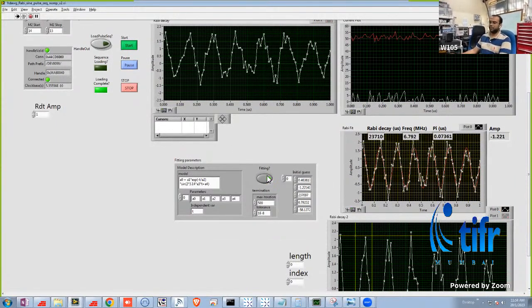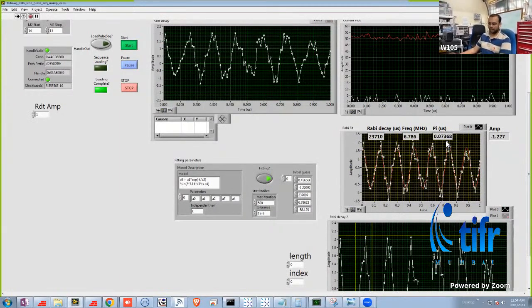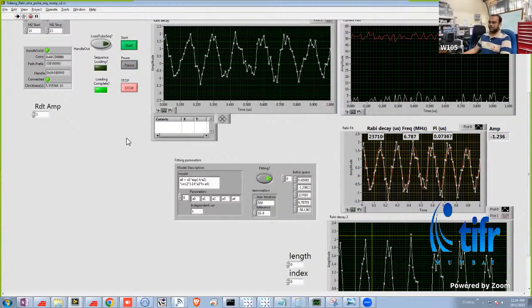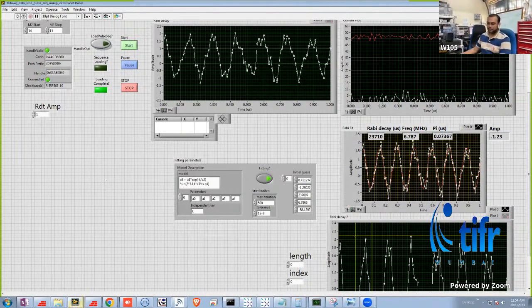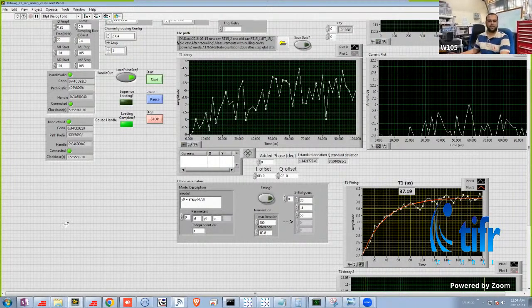Now after that we fit the data to calibrate the pi pulse. You can see it's approximately 74 nanoseconds, and this is how you calibrate the pi pulse. The next thing we want to calibrate is actually to characterize the relaxation time of the qubit. Now the qubit actually spontaneously decays if you prepare it in the excited state.